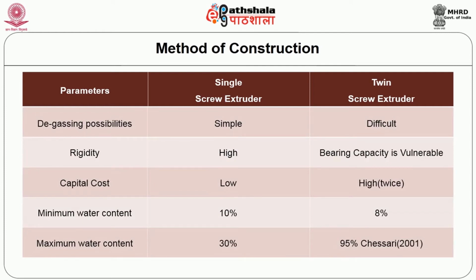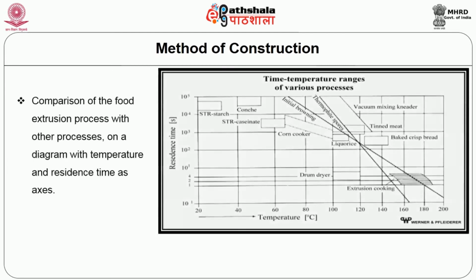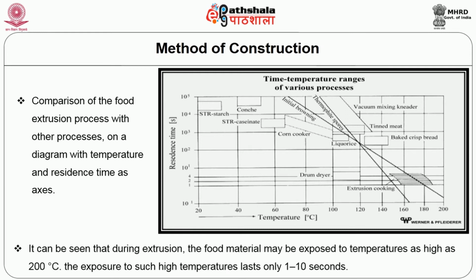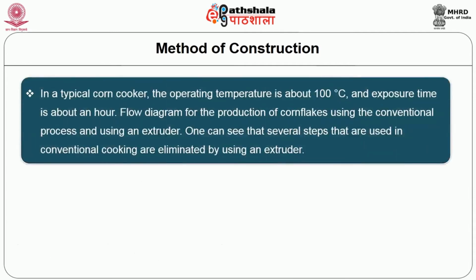Food extrusion is a high temperature short time, that is HTST, process. Figure 3 shows a comparison of the food extrusion process with other processes on a diagram with temperature and residence time as axes. It can be seen that during extrusion, the food material may be exposed to temperatures as high as 200 degrees Celsius. However, the exposure to such high temperature lasts only 1 to 10 seconds. In a typical corn cooker, the operating temperature is about 100 degrees Celsius and exposure time is about an hour.